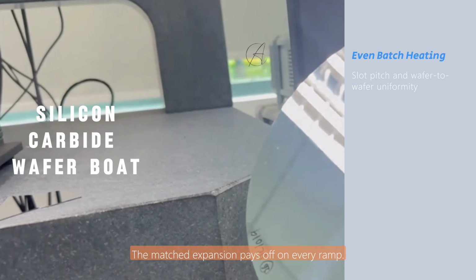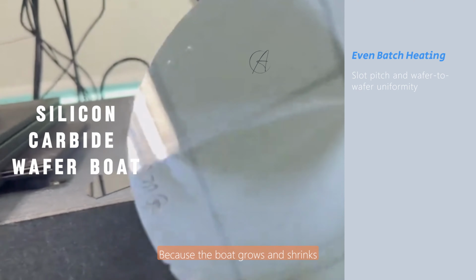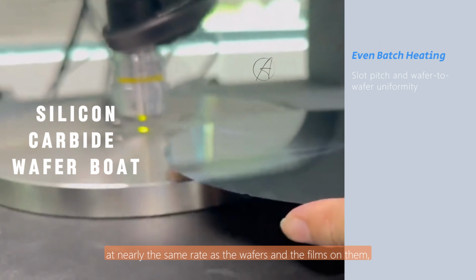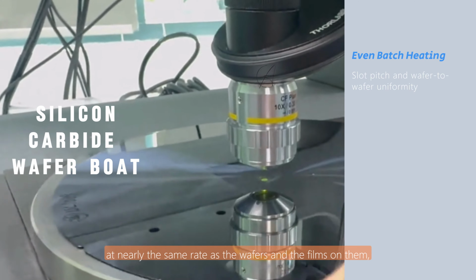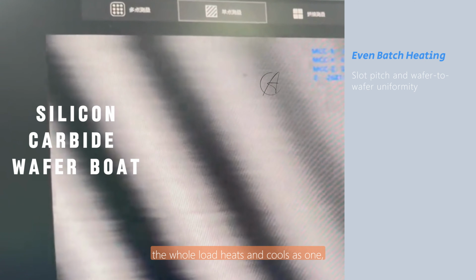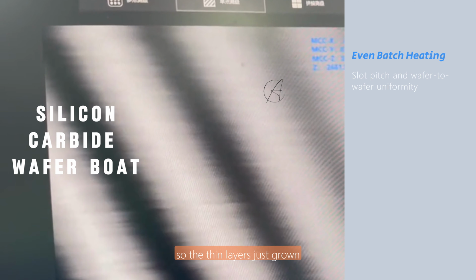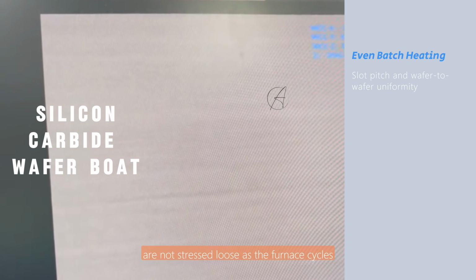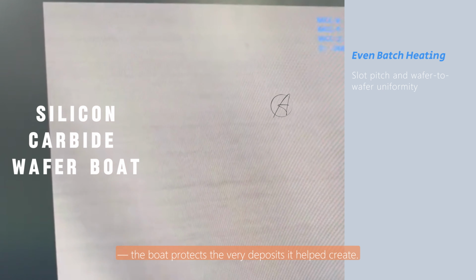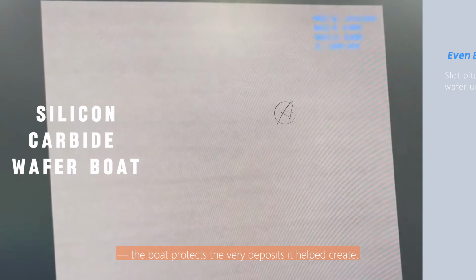The matched expansion pays off on every ramp. Because the boat grows and shrinks at nearly the same rate as the wafers and the films on them, the whole load heats and cools as one. So the thin layers just grown are not stressed loose as the furnace cycles. The boat protects the very deposits it helped create.